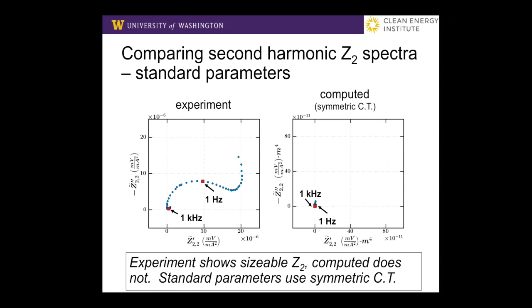So now when we look at the second harmonic and we look at the standard parameters, big differences, big differences. The second harmonic in our real battery that we measure is substantial. We saw that second harmonic peak growing at 1 hertz, and it's substantial. There is virtually no second harmonic in the computation when we have these parameters. And that is largely, it's not just that I've created the axes to do this. It is a very small signal.